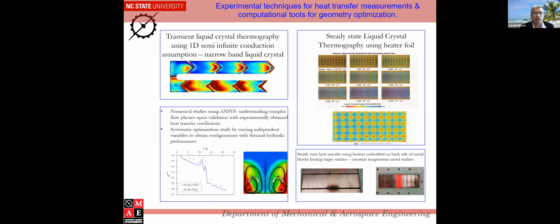about what we do. We do a lot of transient liquid crystal thermography using a 1D semi-infinite conduction assumption, with narrowband liquid crystals. So we get detailed 2D data of heat transfer on the surfaces. This is for impingement on metal surfaces using heater foils. Again, we do CFD to just understand the flow. Again, we can show you some metal-based cooling schemes with heated flows and heated surfaces so that we can actually measure average heat transfer instead of local heat transfer like that.